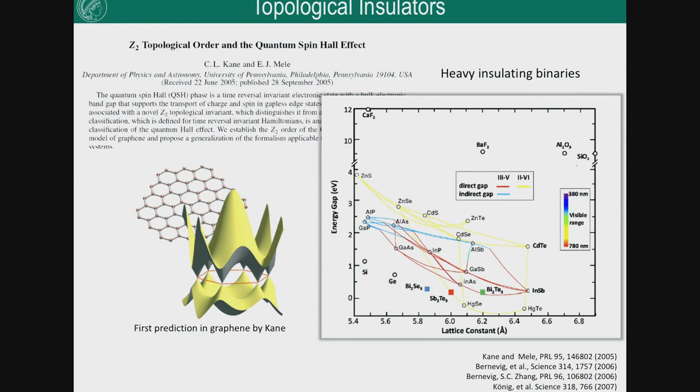They looked for two-element compounds, semiconductors, which are used in electronics and in solar cells. As I said, in solar cells you have a band gap around 2, so the materials you're looking for are cadmium selenide and cadmium telluride, but this was too big. The heavy element compounds very often have very small band gaps and even negative band gaps, and this was why Zhang predicted mercury telluride, because you see it has a small band gap, even a negative band gap.